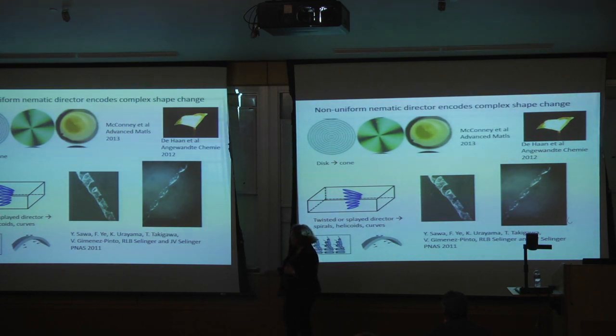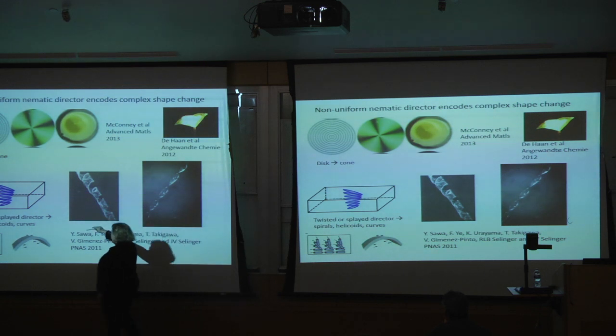We can also induce a twist, just like in the display in your cell phone, or any conventional twisted nematic display. We put a twist in by rubbing the substrates so that on one side it wants to go north-south and on the other side east-west, and we get a 90-degree twist. Again, just like in the display, we add a little bit of chiral dopant. If you have a 90-degree twist and the material's not chiral, it could rotate clockwise or counterclockwise, and you could have domains of each separated by defects. To make sure there are no defects, put in a little chiral dopant so it always twists the same way. In this picture, it's twisting from +45 degrees to -45 degrees, so right at the center of the film, the nematic director is parallel to the long axis of this ribbon.